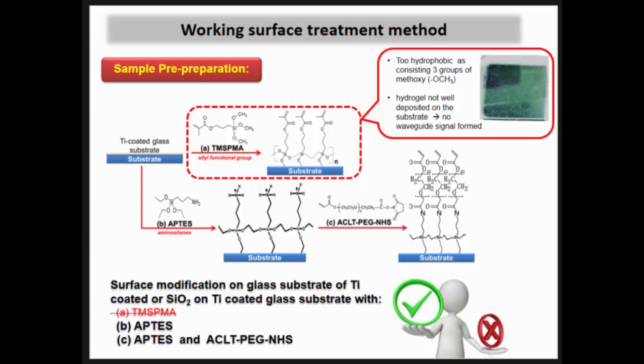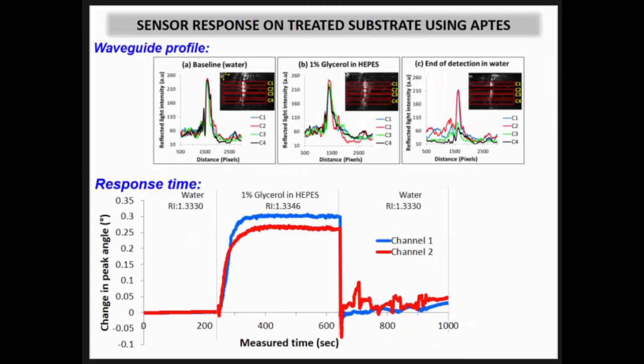So we moved to APTES and acrylate PEG NHS, and I got some results with that. With the substrate treated with APTES, we can get some signal here. However, if you monitor channels 3 and 4, this is using a baseline of water, then this is using a 1% glycerol. And this is at the end of detection, when we remove all the glycerol and flow back with water. If you can see at channels C3 and C4, the peak just decreased, and it indicates that the hydrogel just detached from the substrates.